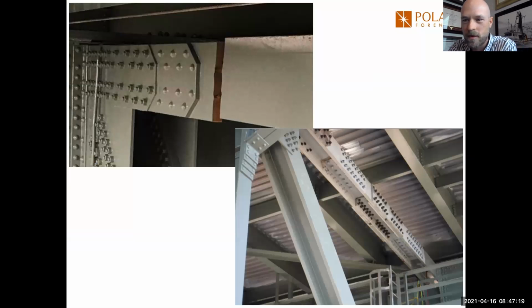Well, it turns out that during these painting operations, on some random day, painters came across this fractured top chord member that you see here. And you can imagine the alarm bells that this set off and the chain reaction that followed. Because of this, they basically closed traffic to the bridge. They had to install temporary shoring, and they had to perform an emergency repair, which is what you see in the bottom right-hand image. They basically spliced that fractured member.